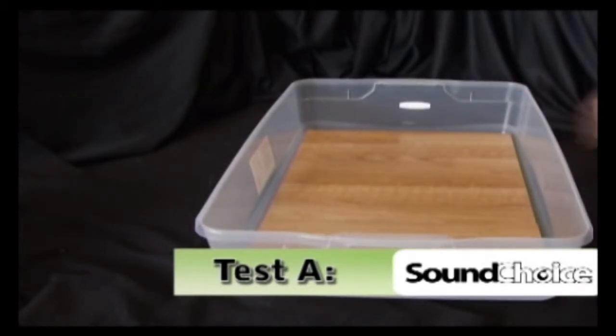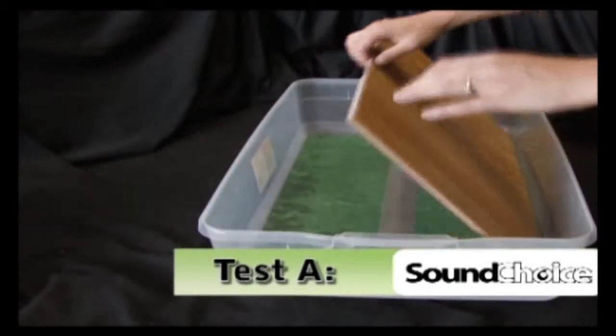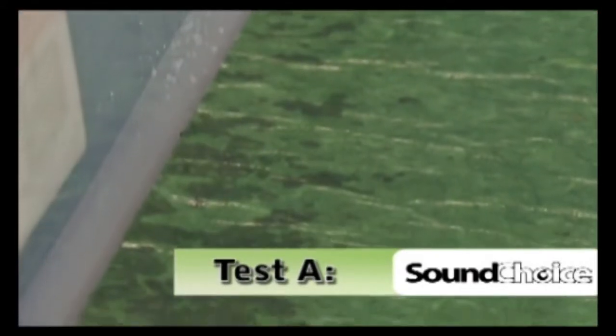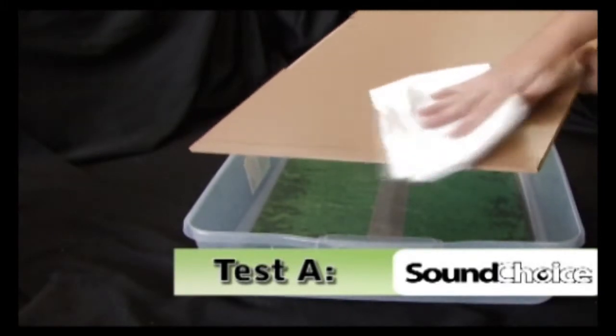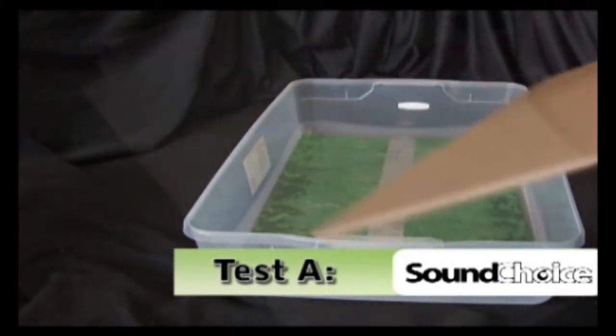The laminate test floor was lifted from one side. There were dark areas below the blue vapor barrier that appeared to be moist. However, both the underside of the laminate and the top side of the underlayment were dry to the touch.